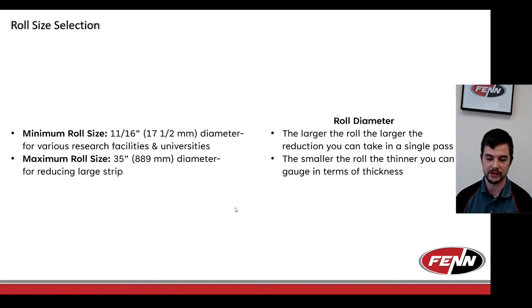Rule of thumb typically, like I said, is that there's a correlation between your roll diameter and how large a hit you can take. There's also a correlation with your roll diameter and how thin you can roll. When talking round wire, a good rule of thumb is that usually you can take about 1/40th the diameter of the roll in terms of a reduction in a single pass. Once that wire has become much more rectangular, much more flat, and no longer has those radial curves to it that make it naturally want to flow to the side as it's being reduced, it usually translates down to closer to about 1/100th the diameter of the roll. So the usual rule of thumb from a grip and reduction standpoint is, the bigger the roll, the heavier the hit you can take.